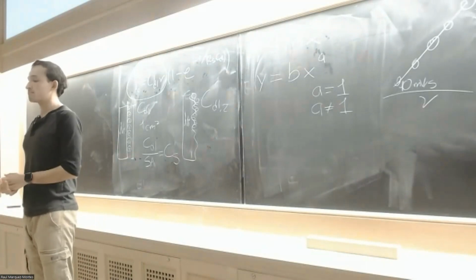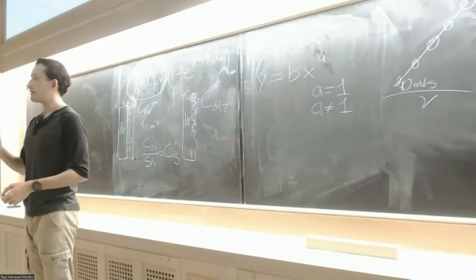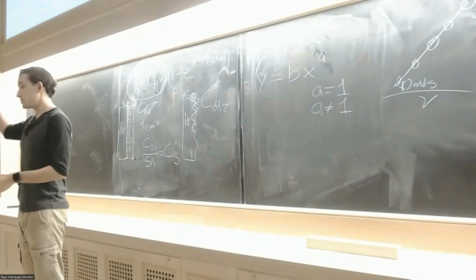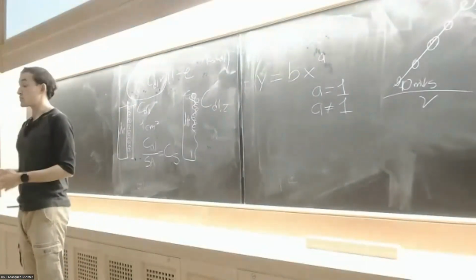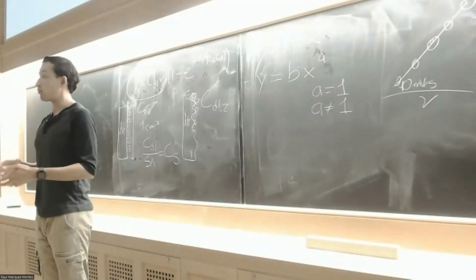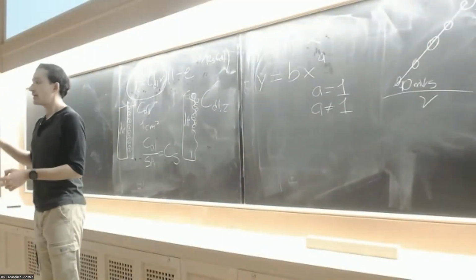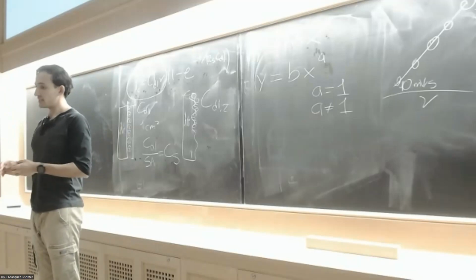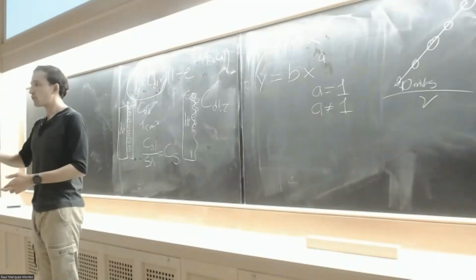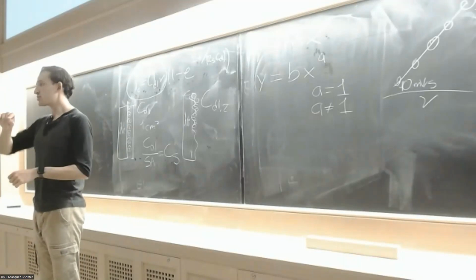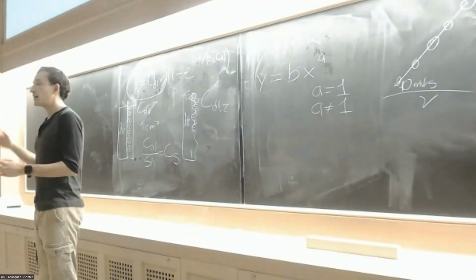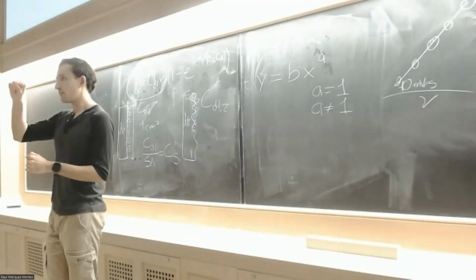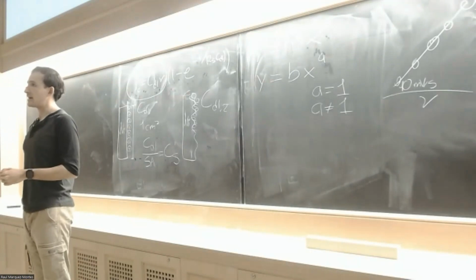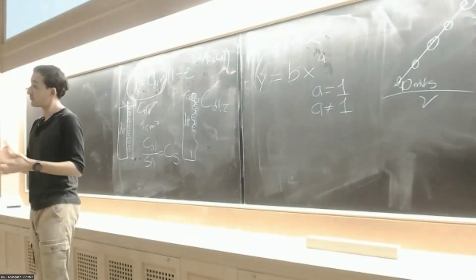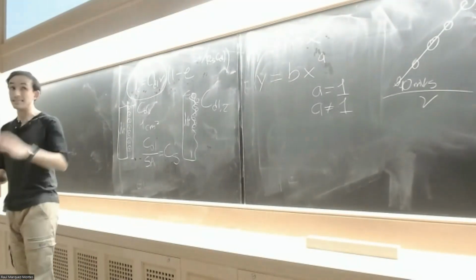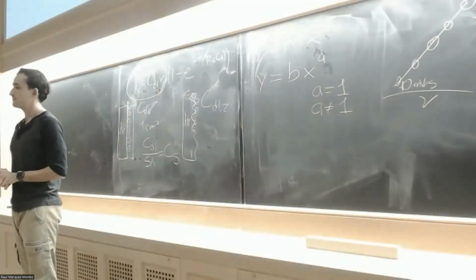So sometimes you can say, for instance, let's get a point every 0.1 millivolts. That means that you will have so many points. Sometimes you can optimize it to use one point every 1 millivolt. And I will say that the best thing to do is just to optimize. Just try different values. Maybe if you use 5 millivolts, you will get a lot of noise. But if you decrease that to 0.1, you will get a more steady response. So I think the best thing to do is always to optimize your conditions first, and then you can get the double layer capacitance with the best conditions.